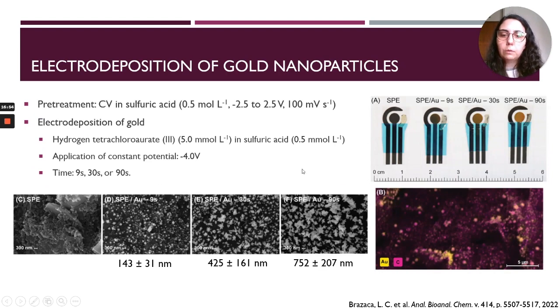So how did we do this electrodepositing of gold nanoparticles? First of all, we had a screen-printed electrode produced by us in PET. So it was a flexible electrode, all made of carbon, and then a reference electrode was painted with silver chloride ink. So using this electrode, we have electrodeposited the gold nanoparticles using a constant potential and different times. So we used 9 seconds, 30 seconds, and 90 seconds.